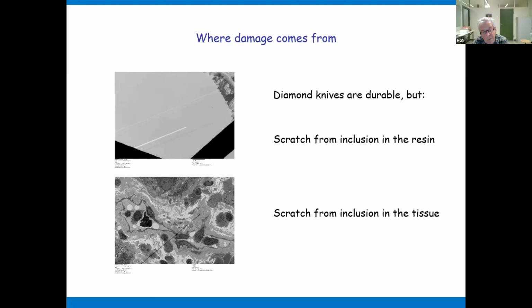It doesn't have to be a very hard inclusion. It's an inclusion, a brittle inclusion in a soft matrix. During the cutting process, it is removed, or at least loosened, and this causes the damage on the knife.